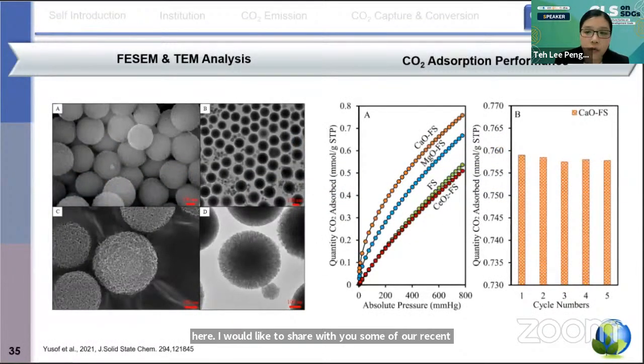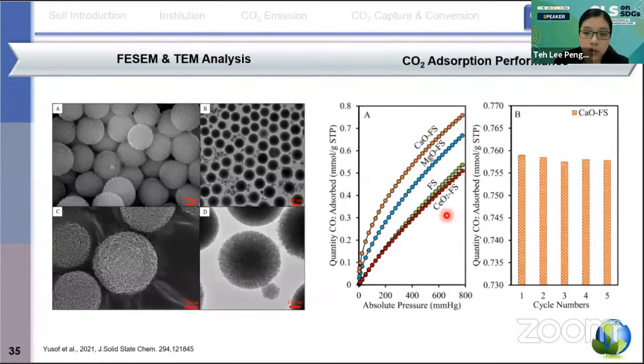First of all, I would like to introduce one of our recent publications on the application of fibrous silica materials with different metal oxides, for example calcium oxide, magnesium oxide, and also silicon oxides, for CO2 capture. We can see here the fibrous morphologies of our materials. This is the FESEM analysis. This is the TEM analysis. And we also tested for recycling, for 5 cycles, to show the potential of these materials.